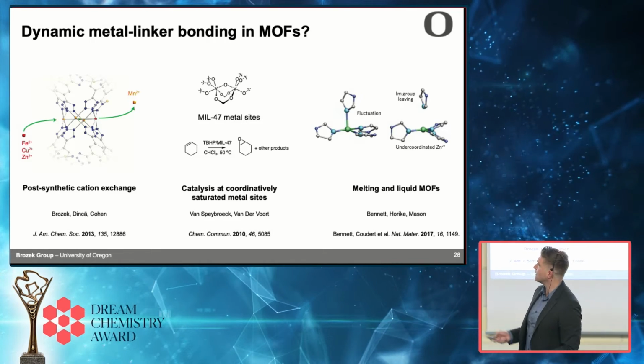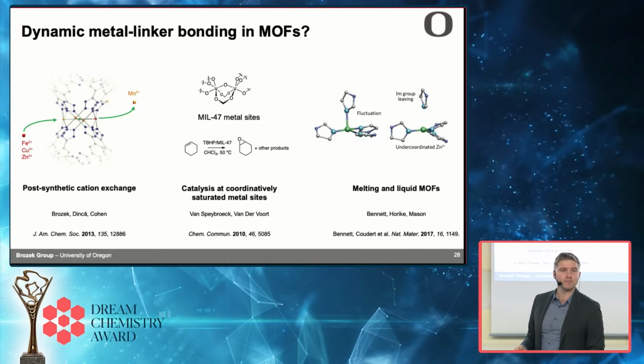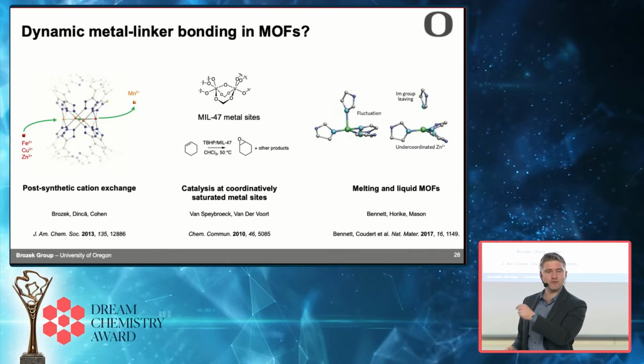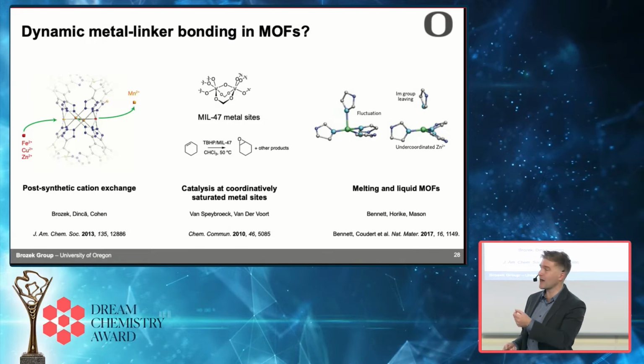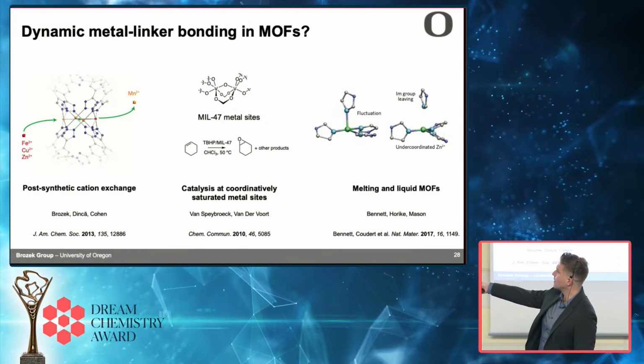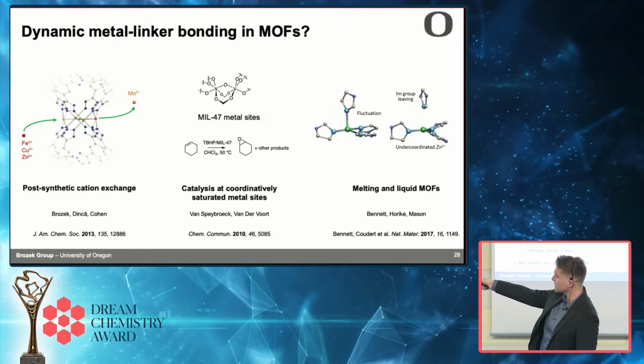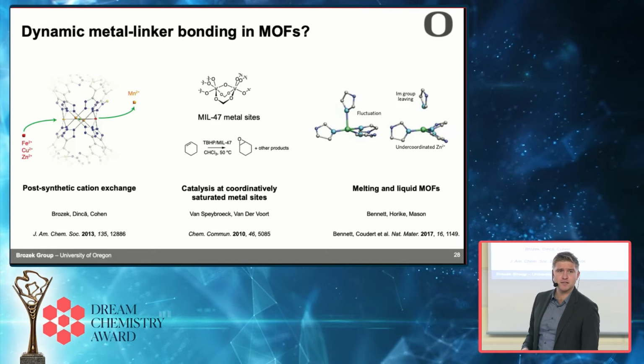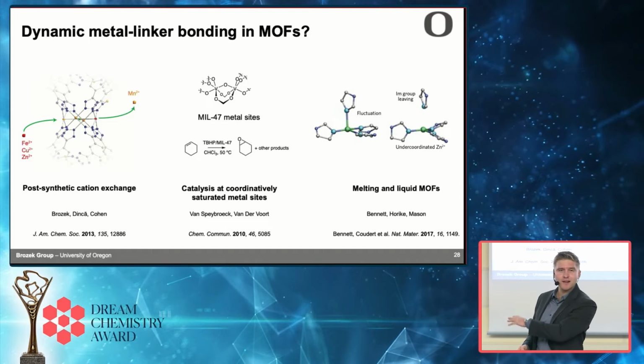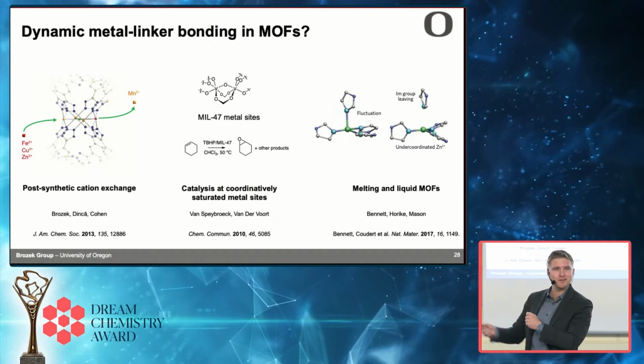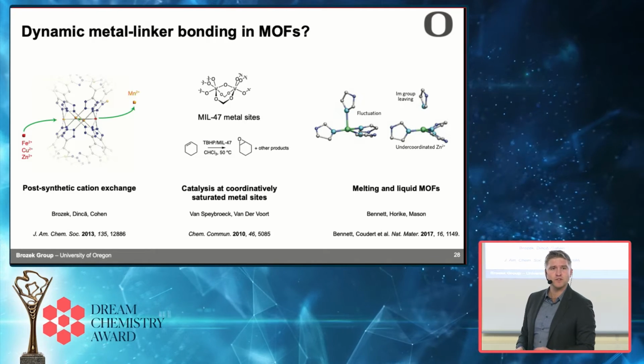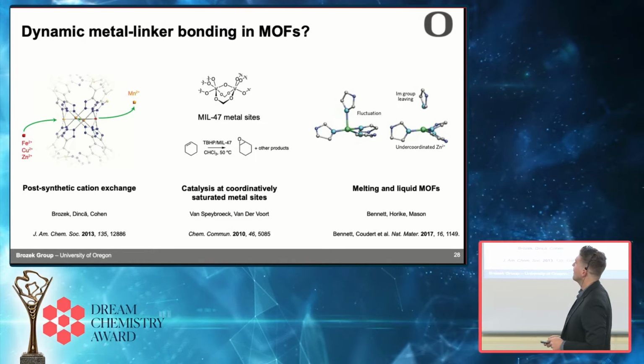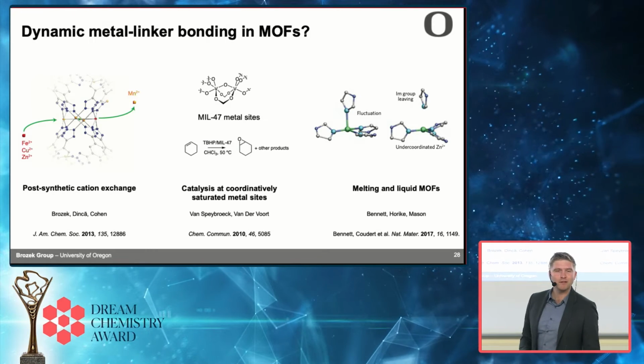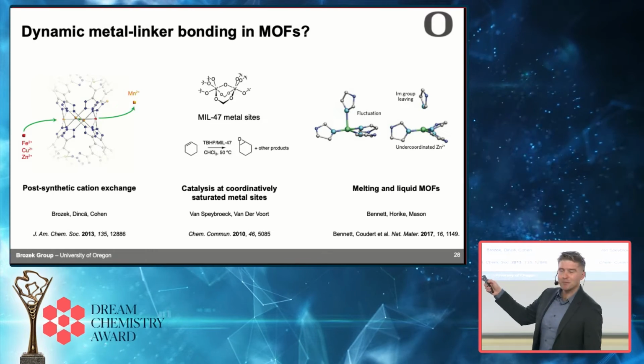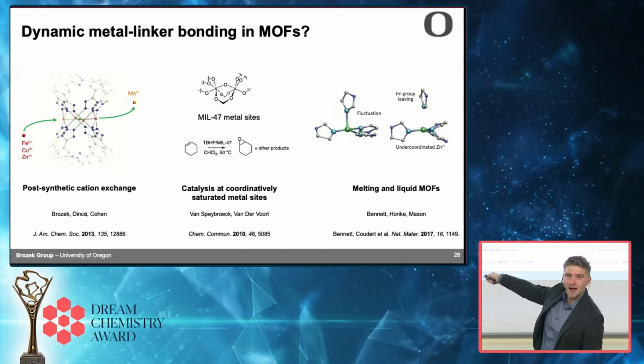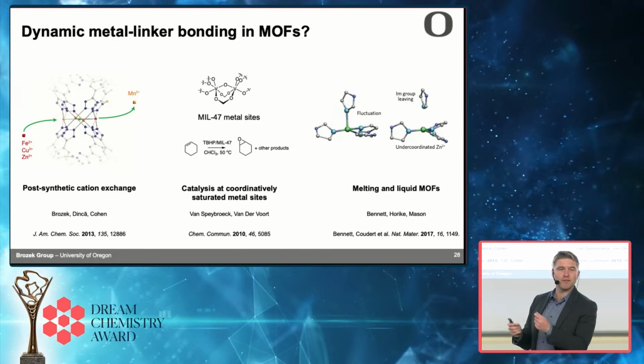It's also known that for some MOFs, the metal sites should be coordinatively saturated, and yet they're able to do the sort of catalysis that would require making metal ligand bonds with your catalyst. So there's this really nice study about the material known as MIL-47, coordinatively saturated, and it's able to perform epoxidation catalysis. And these studies showed it's probably not just defects. I mean, there's a lot of catalysis in MOFs that it's just missing linker defects, but this study was pretty definitive to show that it must be fluxional metal ligand bonds. There's this whole area of melting or liquid MOFs, porous liquids, where in the papers themselves they invoke this idea of dynamic breakable metal ligand bonds as the mechanism of how these things could melt.